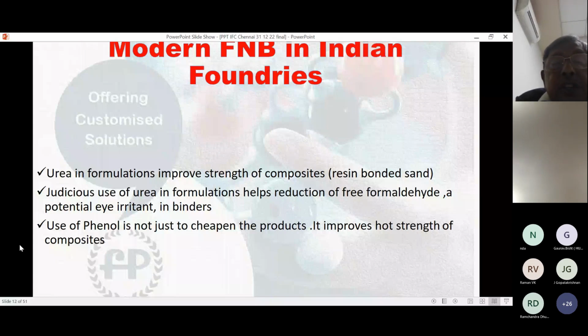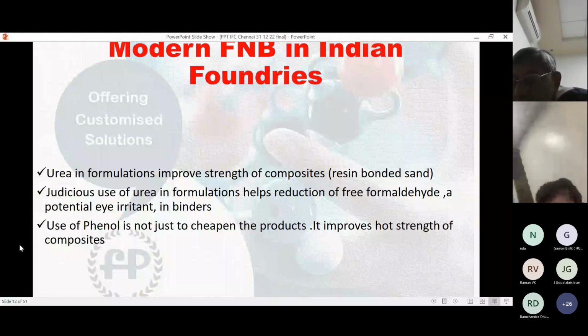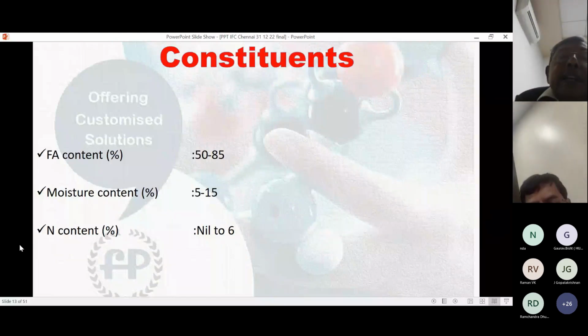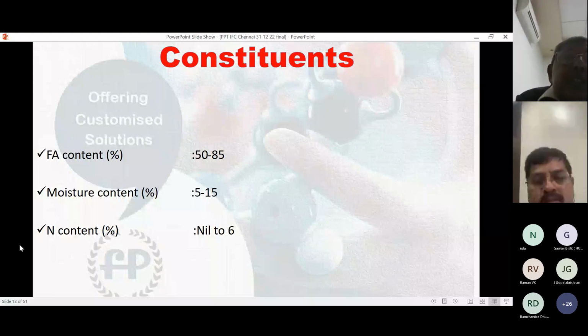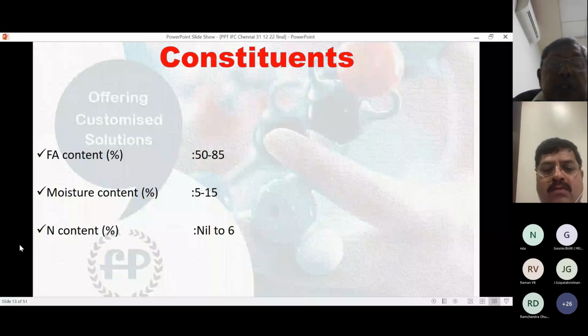Use of phenol is not just to cheapen the products. Many foundrymen believe phenol is added just as a low cost alternate to furfuryl alcohol. No, it has got a cost to be added. It improves hot strength of composites. So this is more or less the formulation and the contents of the furan resin. Furfuryl content 50 to 85, moisture content 5 to 15, nitrogen content nil to 6% in binder.